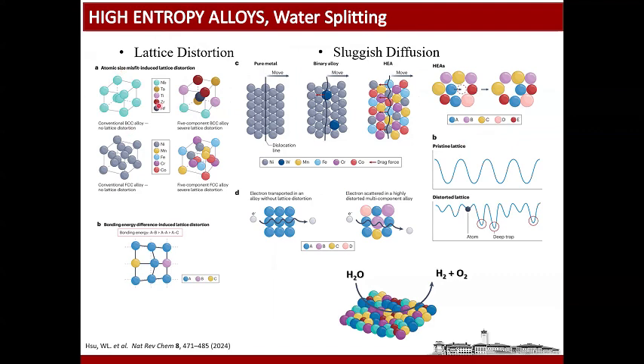In a conventional BCC alloy, there is no lattice distortion, but when you introduce 5 or more metals into the structure, either in BCC or FCC structure, since we now have atoms with different sizes at these lattice points, this will create a severe lattice distortion, and also the binding energies between different atoms are different. So the atom with closer interaction or better interaction with another atom will increase the activation energies, so that will increase the electrocatalytic activity. And also introducing more than 1 or 2 atoms into the structure will prevent the diffusion as well. So this will increase the stability of the structure.